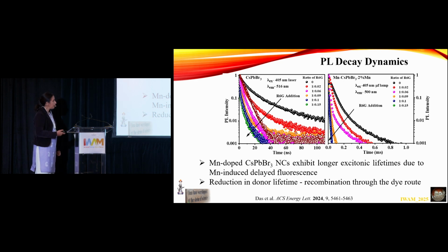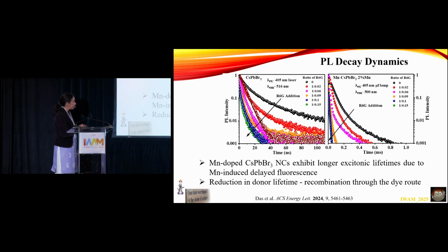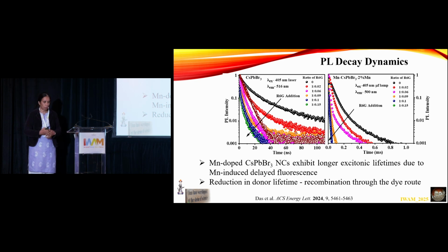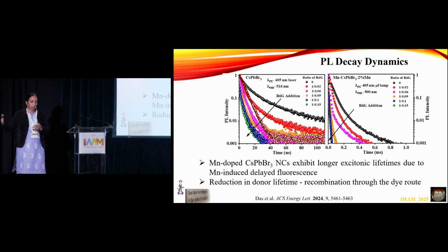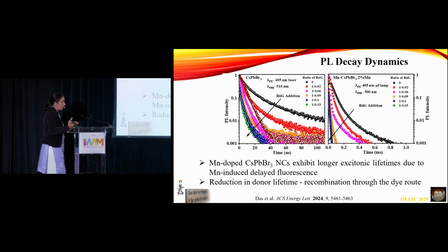Okay, so finally we also observed that with lifetime, you can see that with increasing addition of R6G, the lifetime of manganese is decreasing. The donor lifetime decreases because there is a recombination through the dye route, but of course there are a lot of parameters including IRF problems, which is the resolution of our instrument, because we are going from milliseconds all the way down to a few nanoseconds or even picoseconds. So there are a lot of different instruments used, so we could not quantify that.